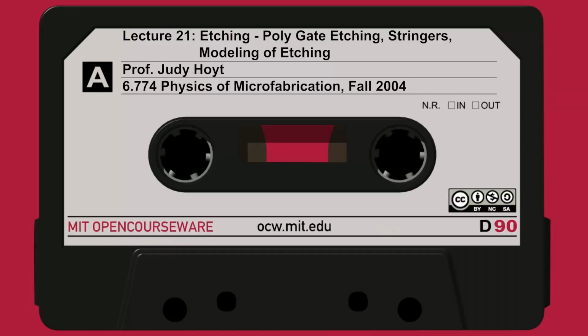Now, why would we care about the gas residence time? Well, we do care about it because the amount of time the fresh gas is resident has to do with the amount of time the gas is available to actually do etching. And if you have a very long residence time, byproducts can develop. After all, these etch reactions are chemical reactions. They evolve byproducts. Those byproducts can then sit there for a period of fractions of a second. And those byproducts can then end up affecting the etch or the sidewall polymer formation or things like that. So residence time ends up being an important parameter.